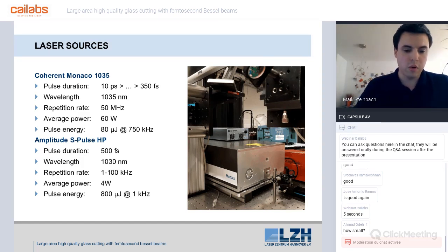The pulse duration is adjustable between 10 picoseconds and 350 femtoseconds. The wavelength is 1035 nanometers. Maximum repetition rate is 50 megahertz with an average power of 60 watts. Maximum pulse energy is 80 microjoules at 750 kilohertz.